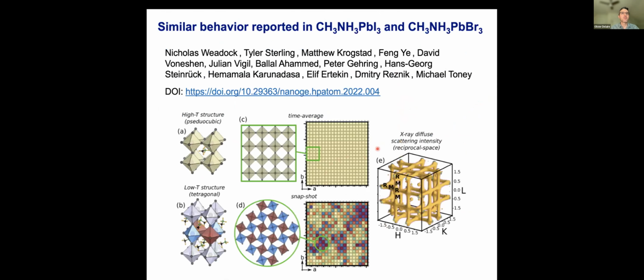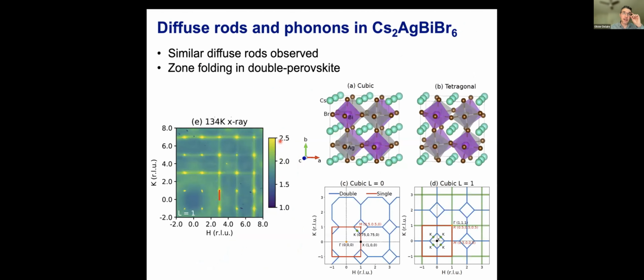So I think there's a work that's published, almost published, from Mike Toney and Dmitry Reznik, where the same rods of diffuse scattering are observed in methylammonium lead iodide and lead bromide systems. So this is really quite general in this family of materials, and this is really further motivating more advanced studies of electron-phonon couplings and complex dynamics.